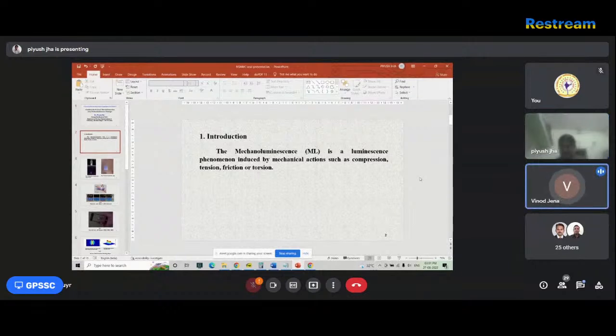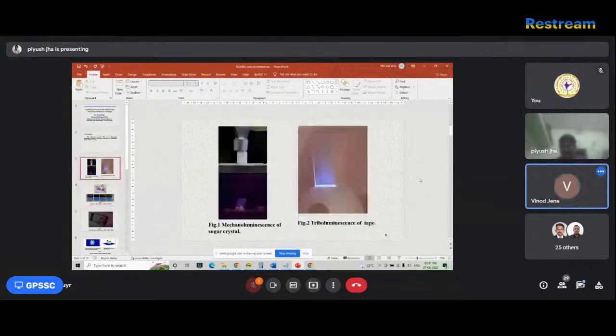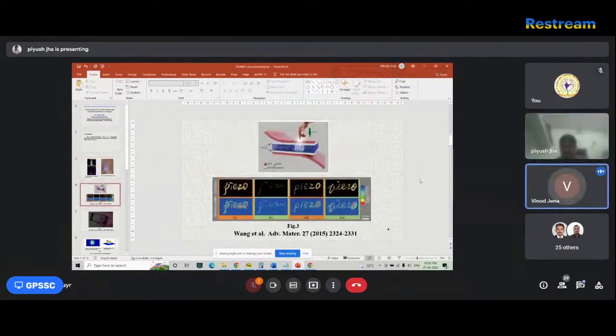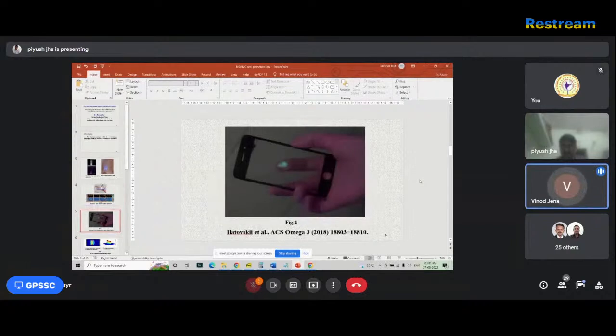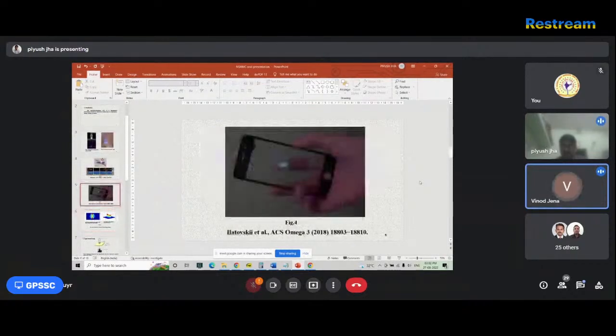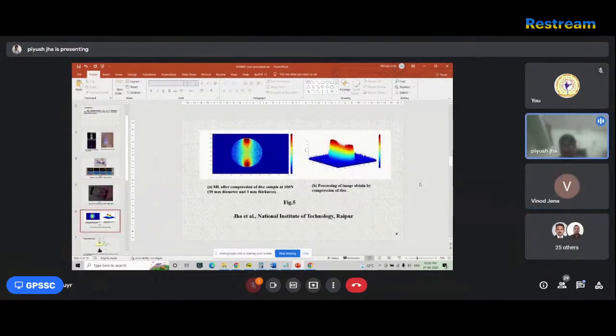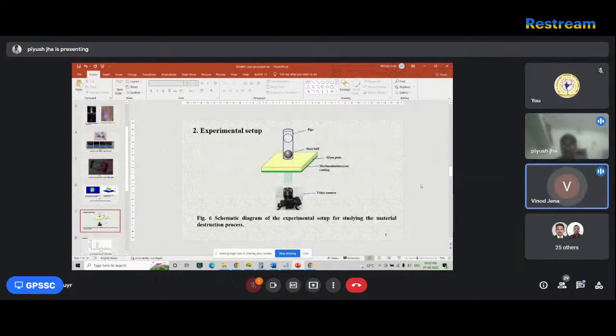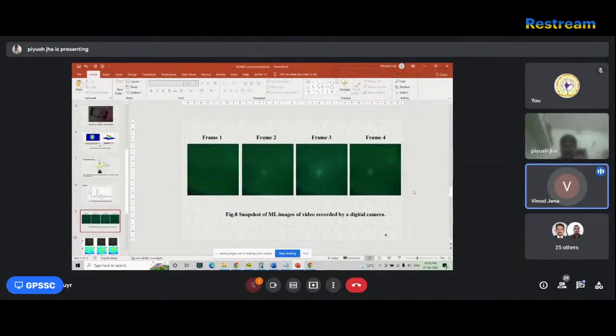In your illuminate, you have doped the europium. Yes, sir. Europium in which oxidation state? +2 or +3? +2. Why not +3? Because +3 is the narrow band. Actually, the mechanoluminescence intensity is more for Eu2+ as compared to Eu3+, but it has a broad band. We use the commercial phosphor. But europium 2+ will show a broad peak in comparison to +3, which is the narrow peak. So why is it chosen for that?